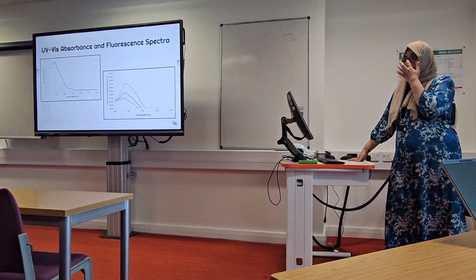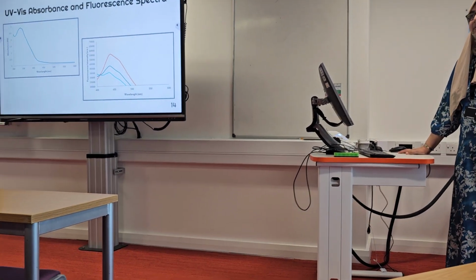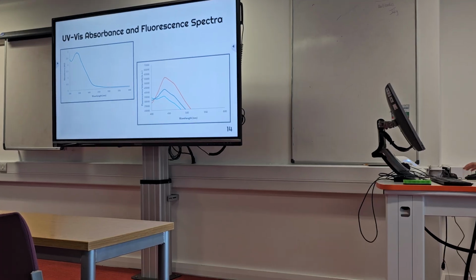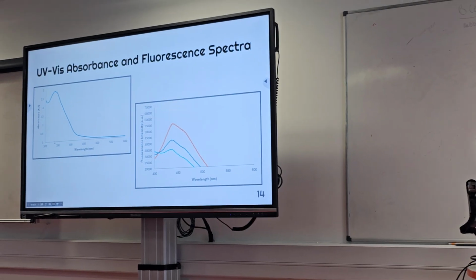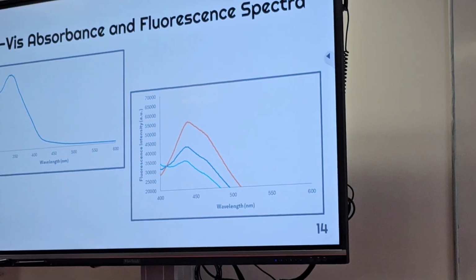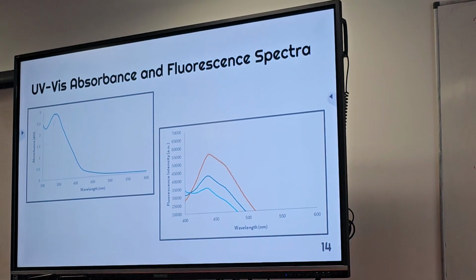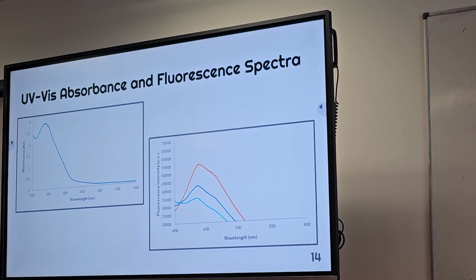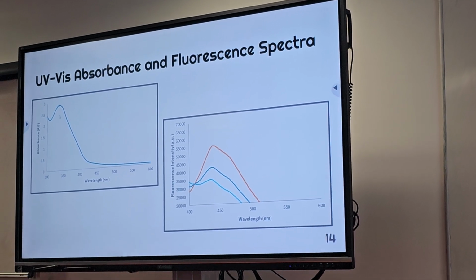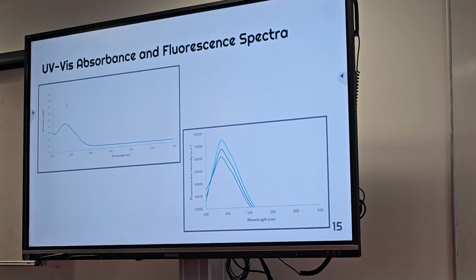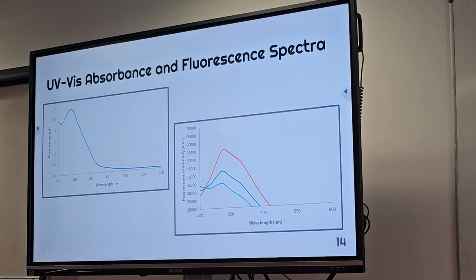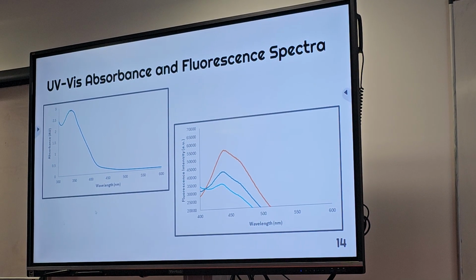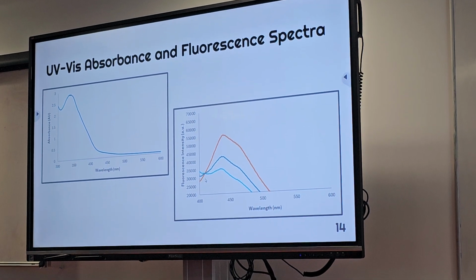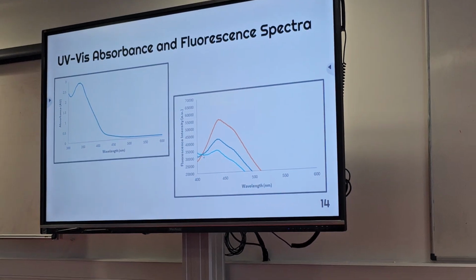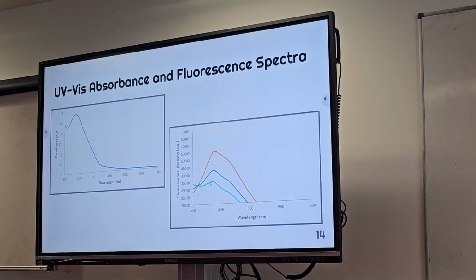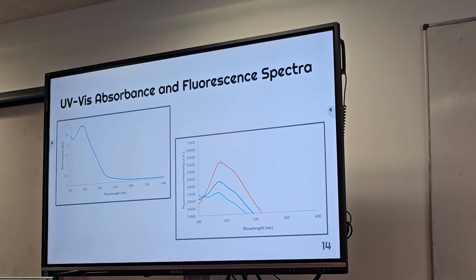So the results. The first result is for citric acid and APTES. The first graph you see here is the UV absorbance, which is around 300 to 350. The peak is at 340, which is higher compared to the other two methods. The second graph is showing the fluorescence. I excite at different wavelengths: the first around 330, second 340, and third 350.